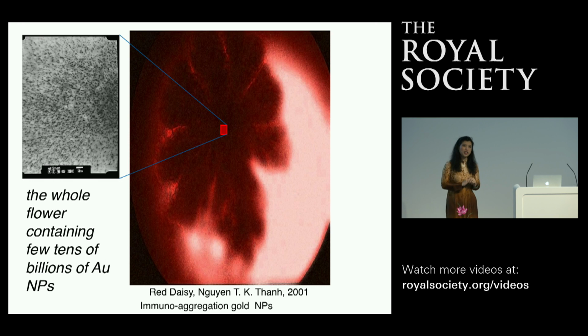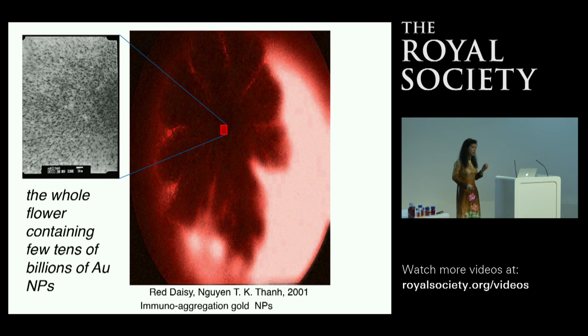Normally, you don't use TEM to characterize the aggregation because it can be mistaken for a drying effect. If you dry a lot of solution, it tends to sediment out, and it can cause an effect like aggregation. But in this case, it definitely shows the aggregation of the nanoparticles due to the immunoassay effect, because we did the control without the antibody, and we don't see the aggregation.